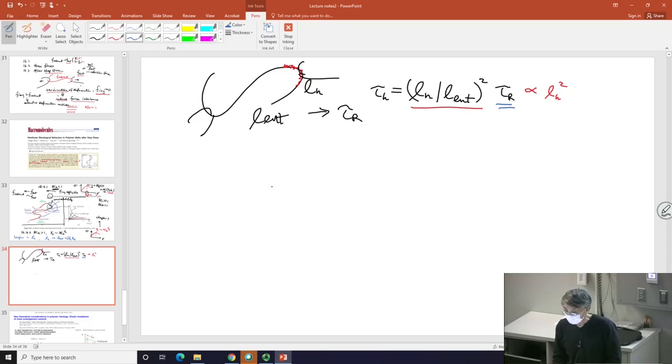So with that in mind about how dynamic the structure is, we can start to use scaling to speculate what is the intermolecular grip force. At the scaling level, this force can be just written down as kT over LH. So that's very handy. I don't have a full theory for this. I'm just doing scaling here. So that's the magnitude of force you have.